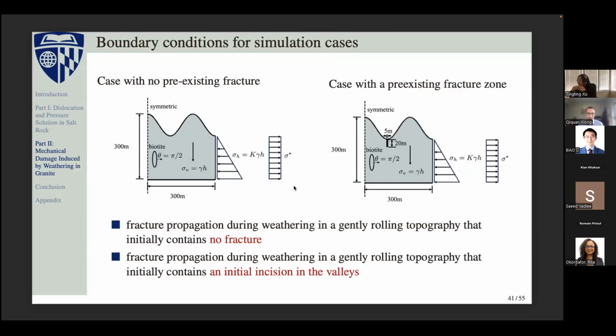And here I show the two different boundary conditions for these simulation cases. You can see that the geometry is pretty similar to the previous simulation cases, but on top of the lateral earth pressure, I also apply lateral tectonic stress. So in this study, we really want to investigate the effect of both the topographic stress and also the tectonic stress. And the difference between these two simulation cases is that in the left one, we didn't insert any fracture.